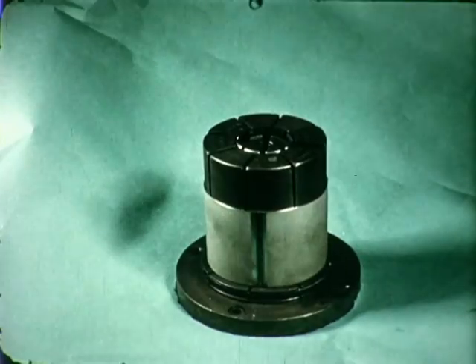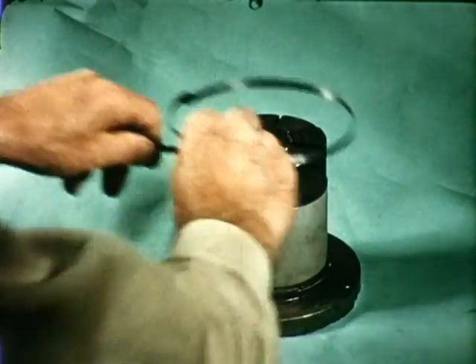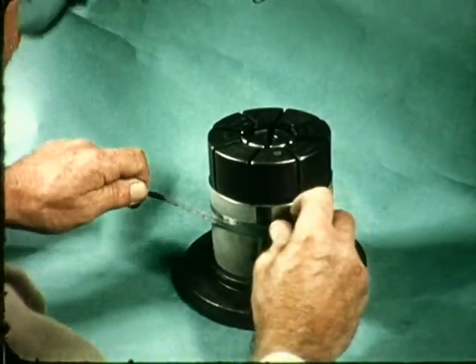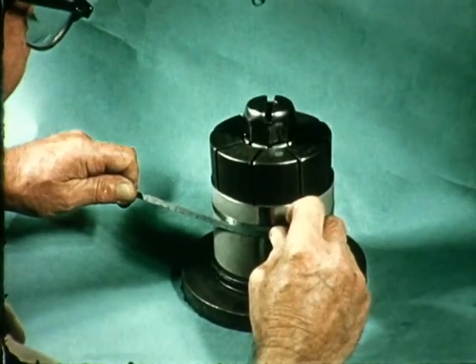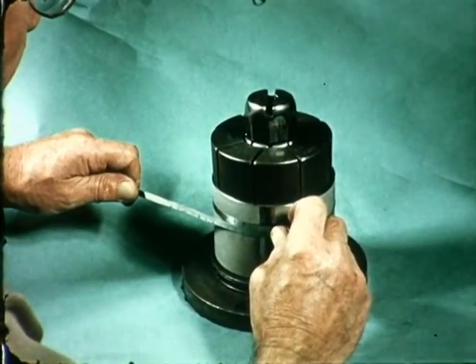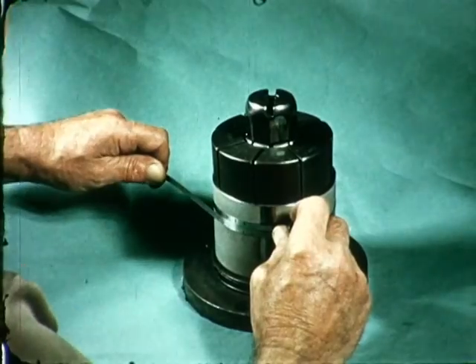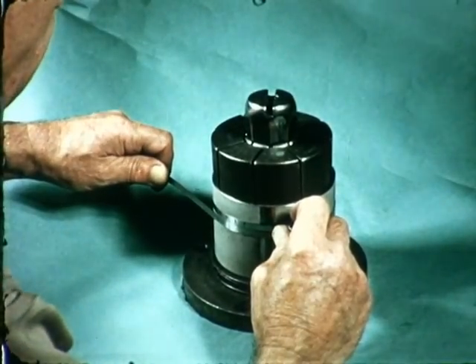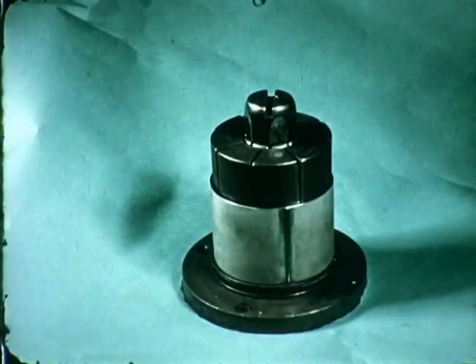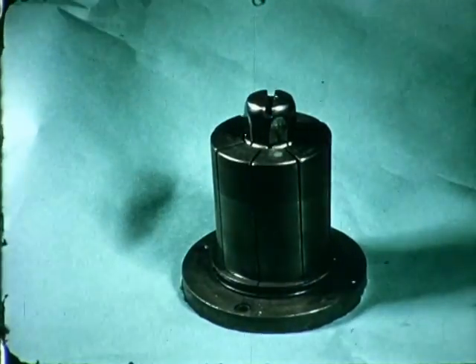As a test, a collar was formed and fusion welded. Subsequently, it was expanded 360 thousandths of an inch in diameter without evidence of failure. The part was expanded 8.9% of its original diameter. This was accomplished in the as-welded condition.